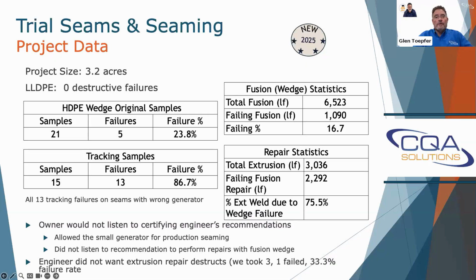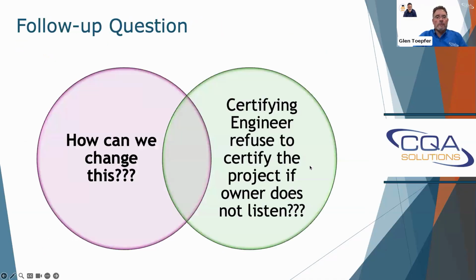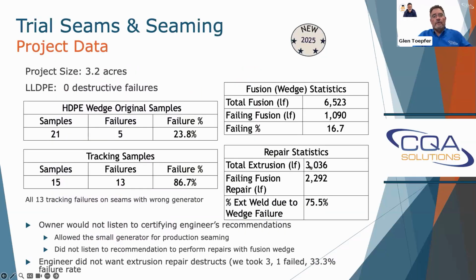And if you look at the fusion statistics, we had 6,500 total feet of fusion welding. Failing fusion welding was almost 1,100 feet, so 16.7% of that failed, and that resulted in repairs. So, we suggested that they fusion weld the repairs, and they went with extrusion welding. So, total extrusion welding on the project for all the repairs and any seams was 3,000 feet, and failing fusion repair 2292. So you had 75% of extra extrusion welding because of those failures, and they could have greatly cut down that number had they just fusion welded with a wedge welder.